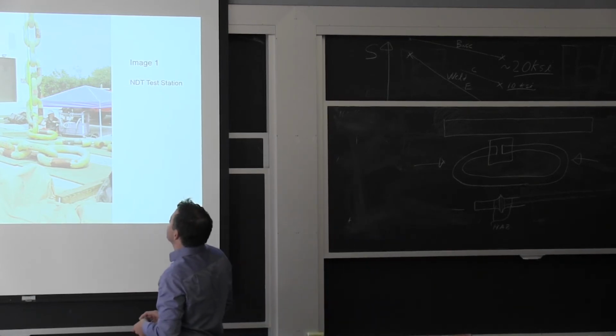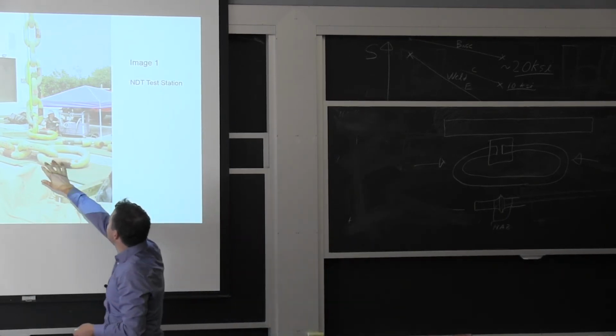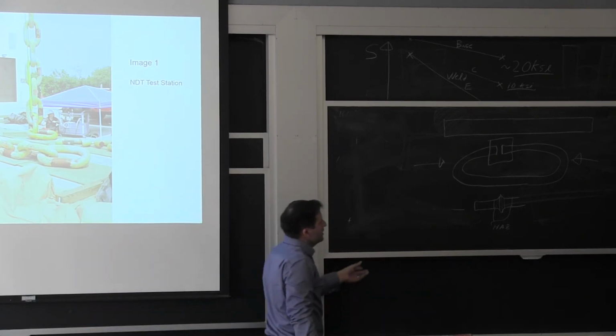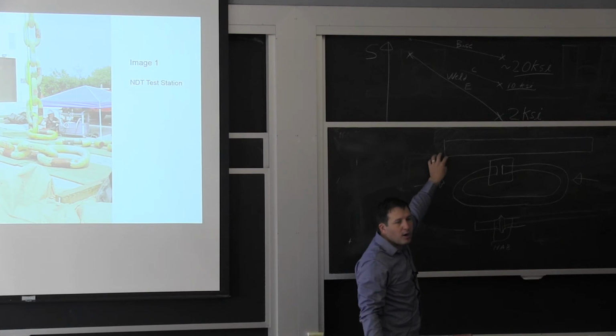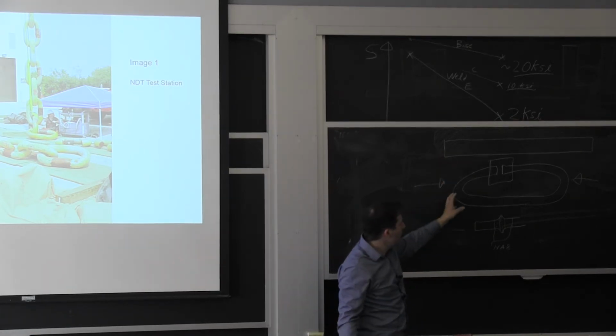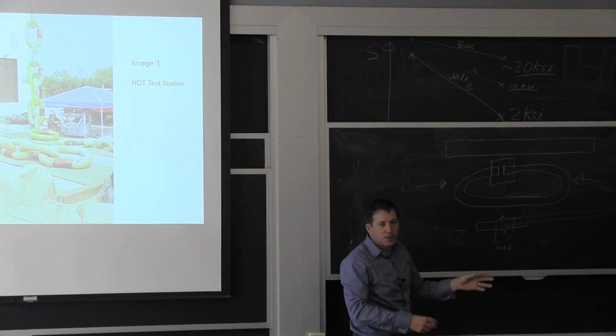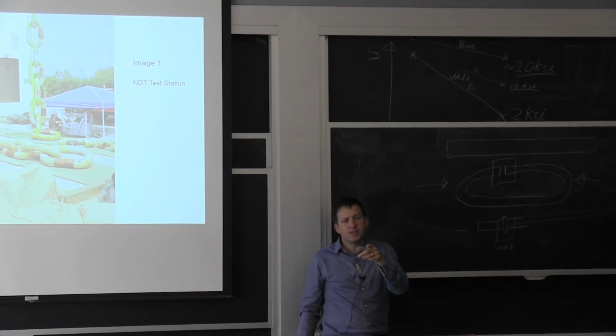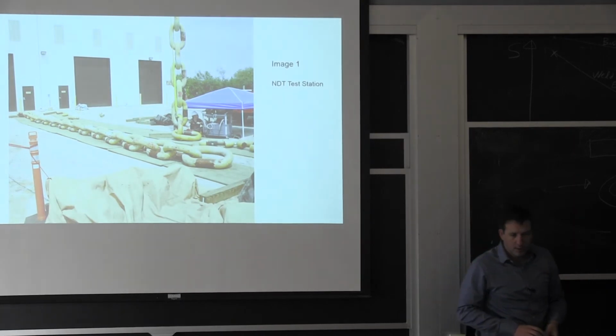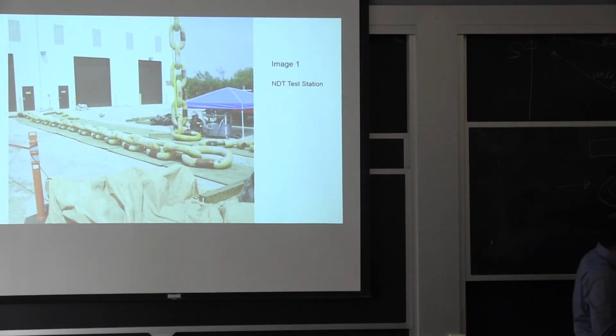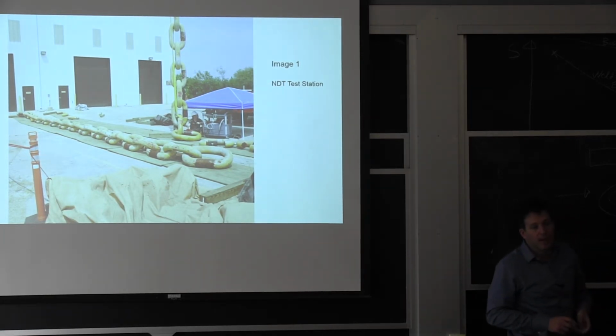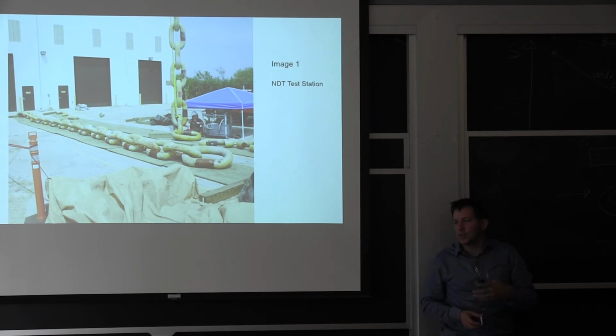Okay, so you can see these are about 4 feet high, 4 or 5 feet high, these chains. And they're made just the exact same way we described, where you start with a flat bar, heat it up, bend it over, apply the current, push it, and then you clean a little bit. And you can see on that chain too that extra material here, the burr, if you will, was just flattened up after the fact. And there are different ways to do it. You can really deburr and clean it so it looks flat and you can't tell. But if you don't mind just a little roughness there, that's what you're looking at getting.